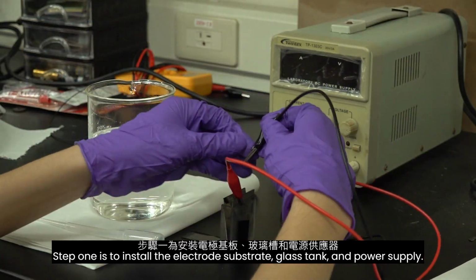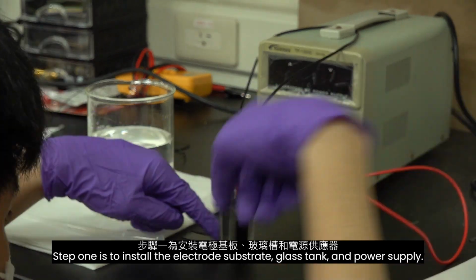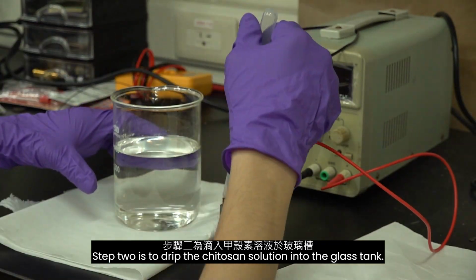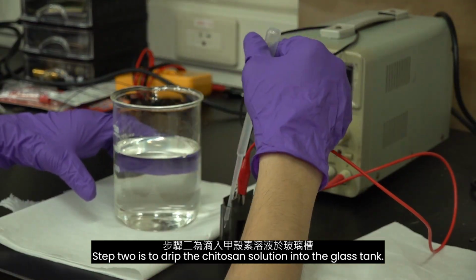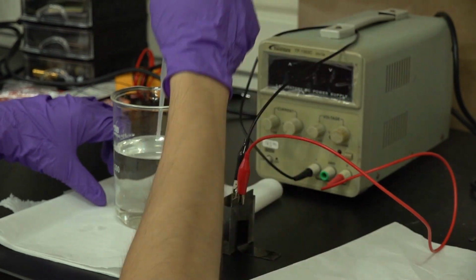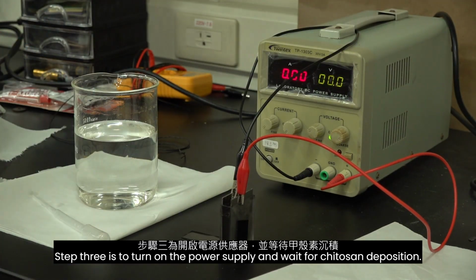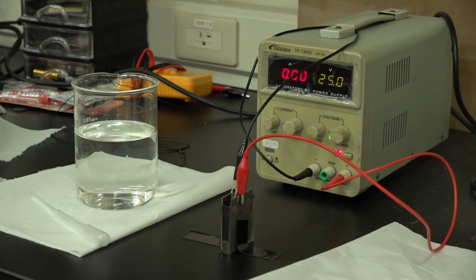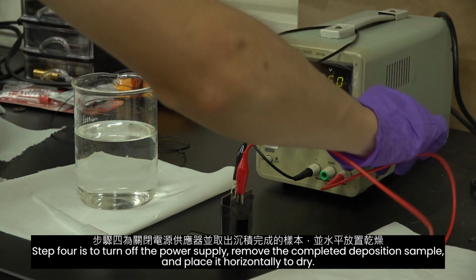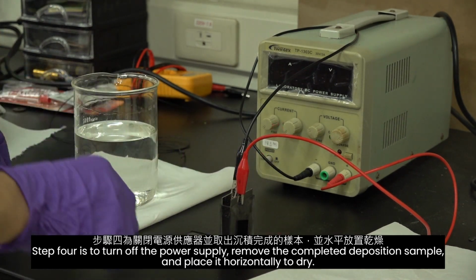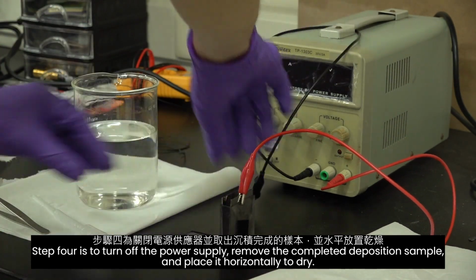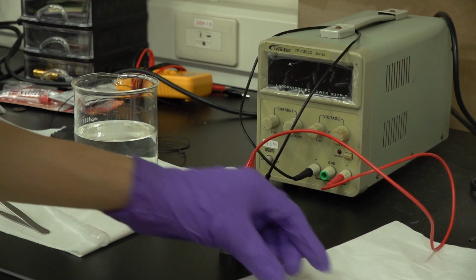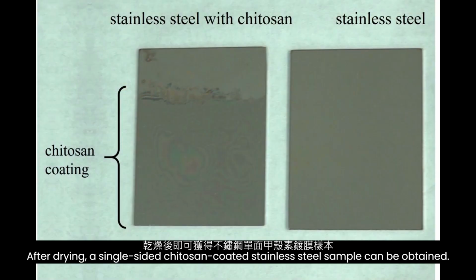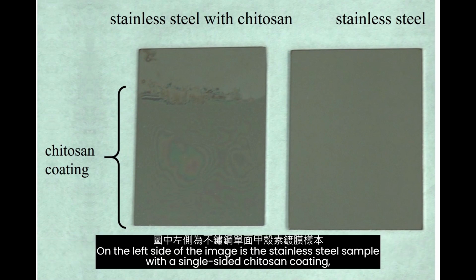Step 1 is to install the electrode substrate, glass tank, and power supply. Step 2 is to drip the chitosan solution into the glass tank. Step 3 is to turn on the power supply and wait for chitosan deposition. Step 4 is to turn off the power supply, remove the completed deposition sample, and place it horizontally to dry. After drying, a single-sided chitosan-coated stainless steel sample can be obtained.